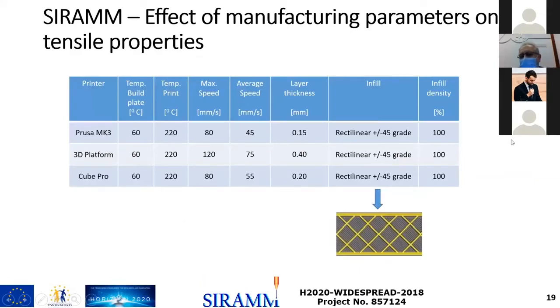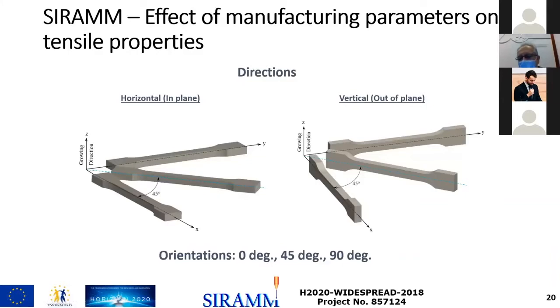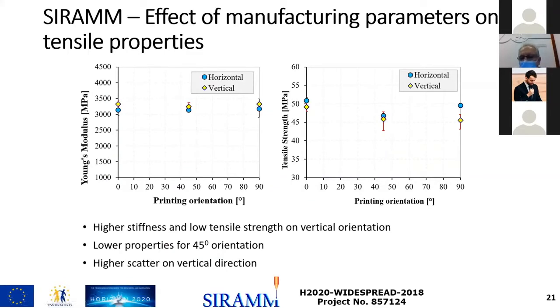We use 100% infill and rectilinear plus minus 45 degrees infill with 100% density with different layer thicknesses from 0.15 millimeters to 0.4 millimeters. We printed the specimens in two planes, horizontal and vertical, and we consider three different specimen orientations. Here are the Young modulus and the tensile strength. What we see, the difference between the two planes is not so big, but anyway, we get higher stiffness and lower tensile strength when the specimens are printed vertically. The lower properties were obtained for 45-degree orientation, and also in the vertical direction, we have quite a high scatter.